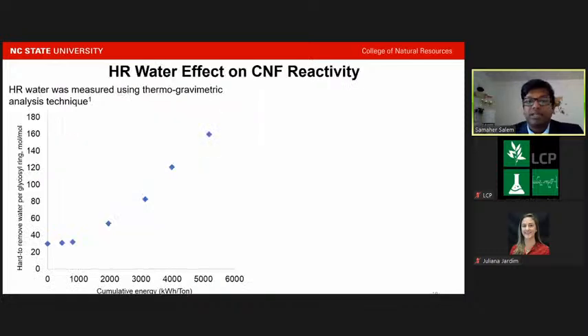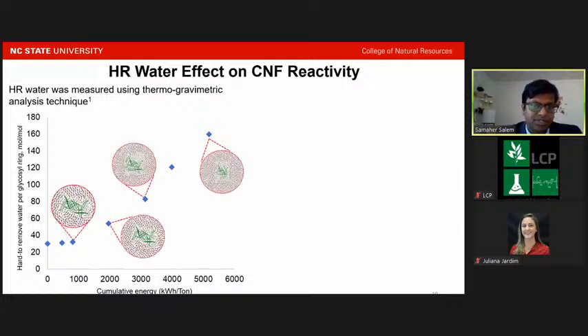And what we did, for each sample, we could say that with the increase of energy, the hard to remove water per glycosyl ring, represented per mole, increases drastically. And after surpassing 3000 kilowatt hour per ton energy, it's really, really high. It increases exponentially. And we could say that due to this increase in the hard to remove water, the number of hydration shells around the cellulose nanofibrils increases. This increase in the hydration shell decreases the reactivity of the cellulose nanofibrils after reaching the maximum reactivity.